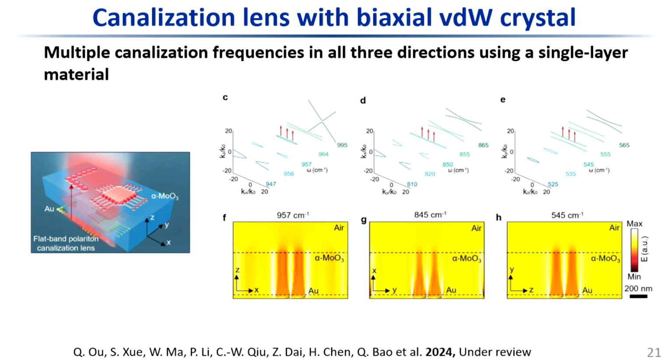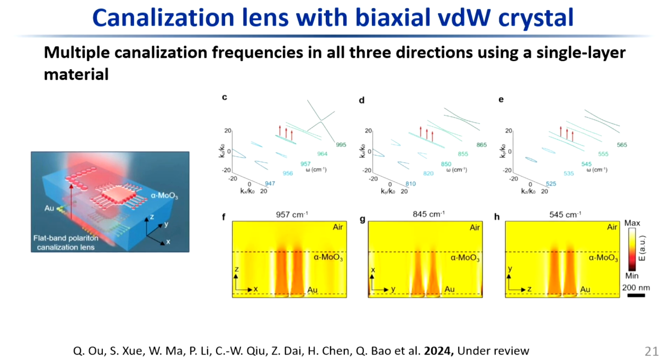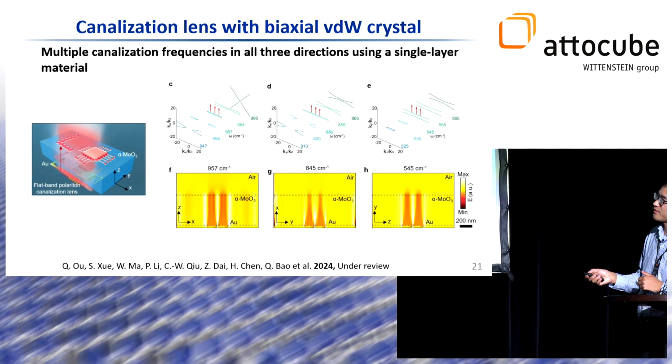This is a cross-section simulation. If you place the MoO3 crystal on top of two closely packed disks with a narrow gap like 50 nanometers, we can clearly see the directional propagation of phonon polaritons, and at the top surface of MoO3, you can clearly resolve that narrow gap. And it can be achieved in three directions.